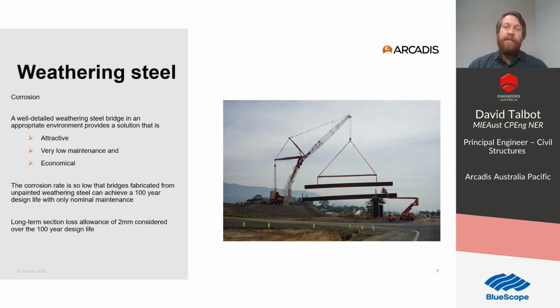So just to touch on the corrosion, and particularly the corrosion allowance that we made for these Berry to Bomaderry projects. Weathering steel needs cyclic wetting and drying to form properly, so it's not suitable for use in every location. It's also subject to normal other durability considerations. The patina doesn't form well with high chlorides or other environments that are quite aggressive. So first of all, you need to assess your site and see if it is suitable for weathering steel. When used in the right locations, weathering steel can be quite an attractive product, very low maintenance and economical, particularly for the long term, because of that reduced maintenance requirement.